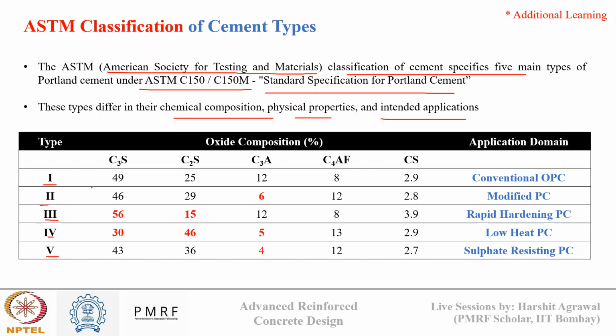In type 1 cement, it is just a conventional OPC. Okay, ordinary Portland cement. So we can see from the proportion, C3S is around 50%, C2S 25%, C3A 12%, C4AF 8%, and calcium sulfate is 2.9%. And it is a conventional OPC system.